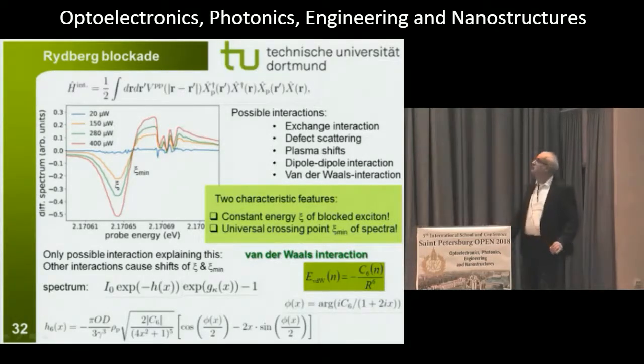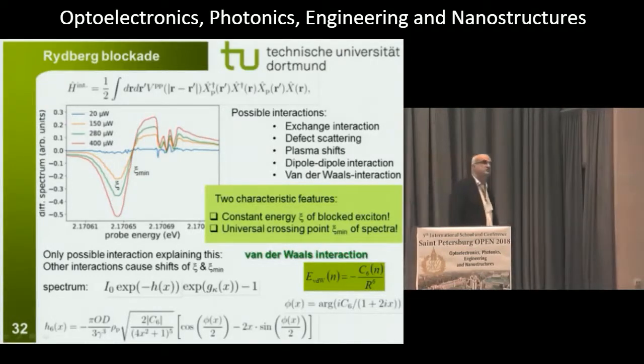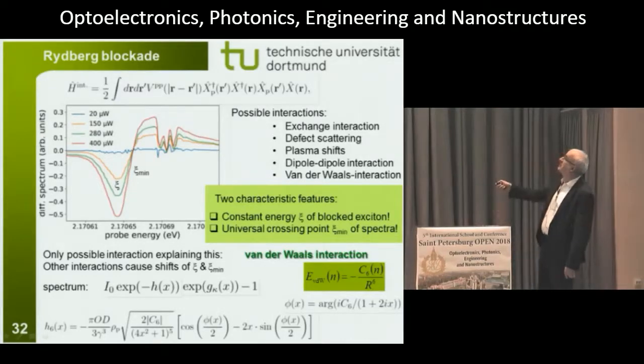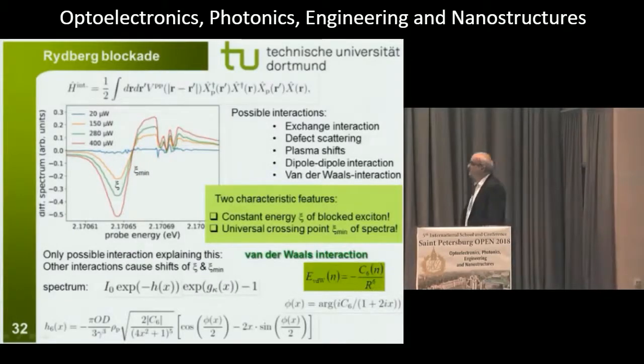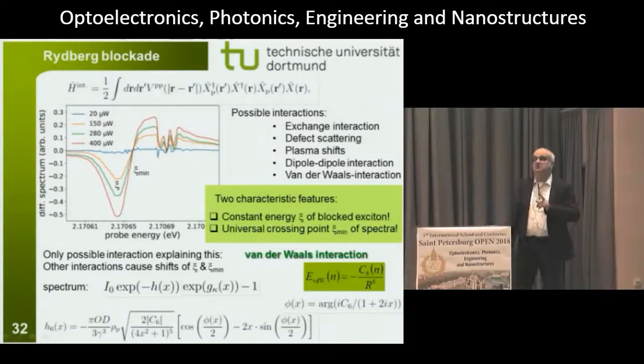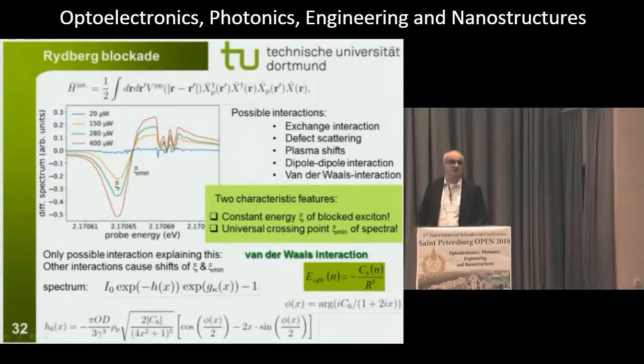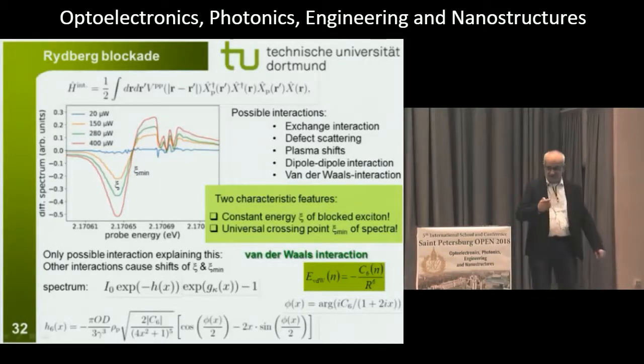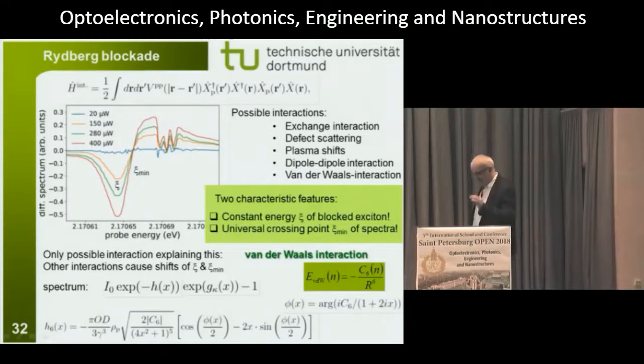And in the literature, you find a lot of different possible interactions between excitons, like exchange interaction, defect scattering, plasma shifts, first dipole-dipole, van der Waals interactions, all is possible. So we checked all these mechanisms by calculating the exciton spectrum. I have no time to go through the details, but we found out that only a single interaction gives you this characteristic behavior, that the absorption line becomes bleached without any energy shift, and that you have this universal crossing point here, and this is the van der Waals interaction. Yeah, and with this, I don't go into the details. This is heavy quantum optics calculations. You can describe all your spectra. So the result of these studies is that we finally understand the interaction between excitons, and this is a van der Waals interaction.